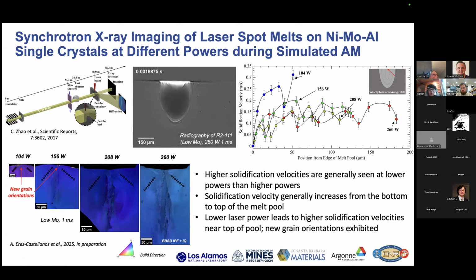This is in collaboration with Teresa Pollock's group at UCSB. Teresa provided us some nickel moly aluminum single crystal samples, and these were given to us as pigtail single crystal castings. The neat thing was then we could strategically cut out specific orientations to look at and do these really clean studies. And now here we're doing synchrotron X-ray imaging of these single crystals with different power conditions, doing simulated additive manufacturing.